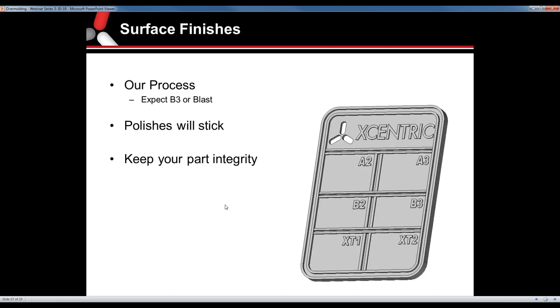Surface finishes: we look at whether we put a B3 — which is a basic rough polished 320 paper — or some type of bead blast with a media. Those range from very light to very heavy texture depending on your application. Some polishes will stick on the overmold itself, so depending on the material, you have to dial in what type of texture or polish you should be applying. We do have texture plaques available to anyone that wants them — just send us an email at sales@eccentricmold.com. It shows our standard finishes and textures in different materials and colors.